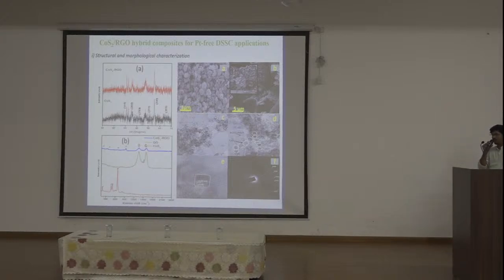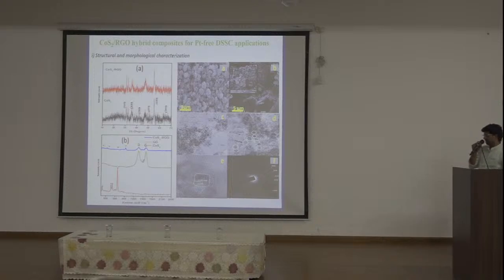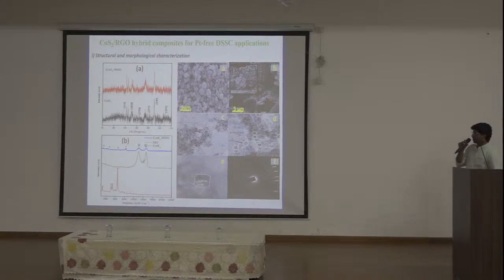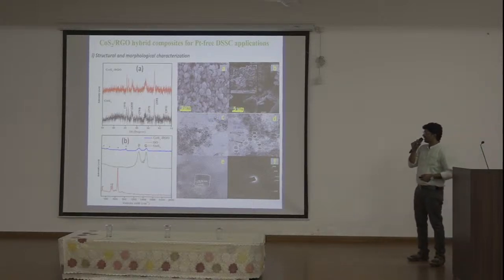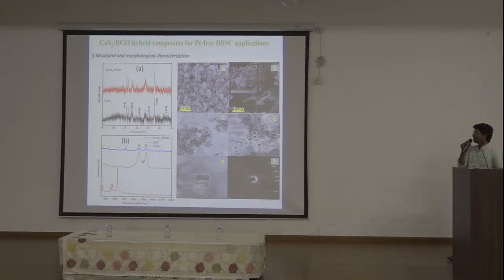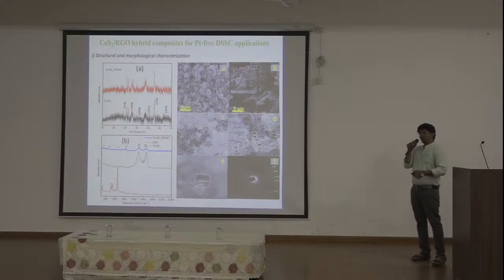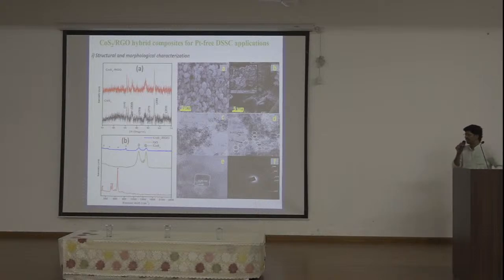And here we can see the Raman spectra, a clear idea of the vibration modes present. We can conclude the composition as well as the vibration modes in this composite material. We can see the cobalt sulfide material along with the cobalt sulfide RGO nanocomposite, with the characteristic vibration modes of cobalt sulfide. There are two bands, at 1350 and 1550 inverse centimeters, the D and G bands. For graphene oxide prepared by the modified Hummers method, hydroxyl and carboxyl functional groups are attached on both sides, so the disorder and defect structure indicate the D band. The G band is due to the in-plane vibration of carbon atoms.